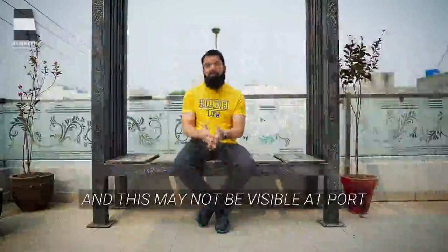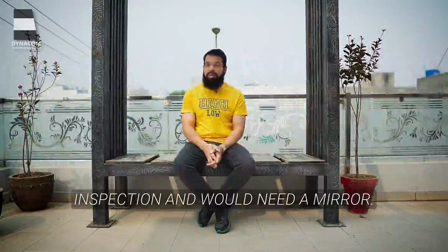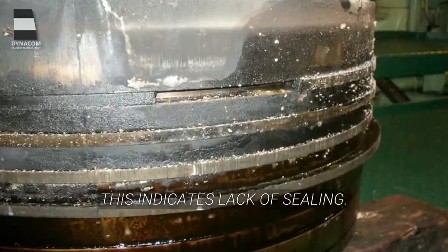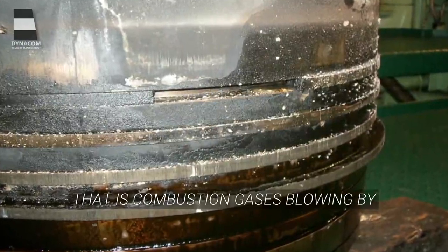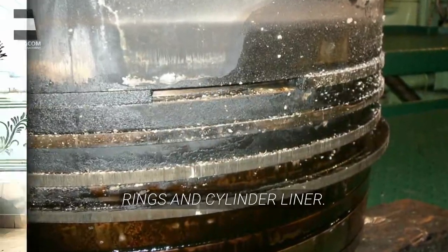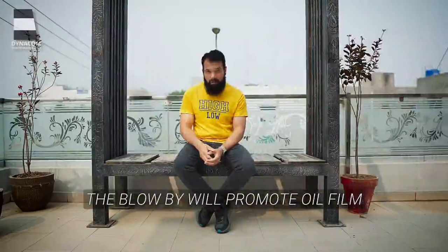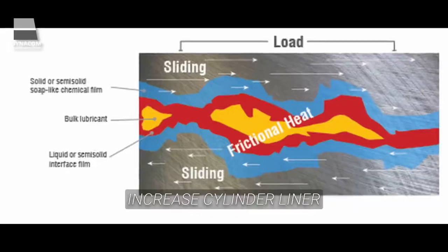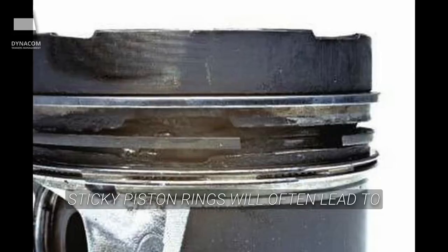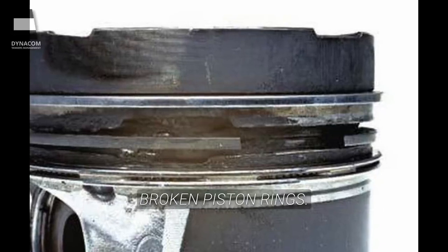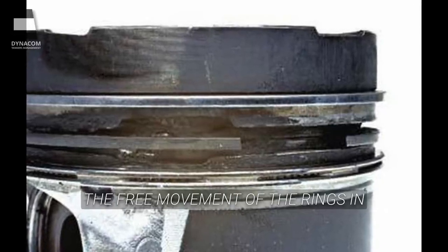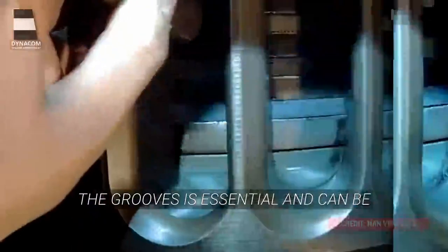And this may not be visible at port inspection and would need a mirror. This indicates lack of sealing, that is, combustion gas is blowing by between the piston rings and cylinder liner. The blow-by will promote oil film breakdown, which in turn will increase cylinder liner wear. Sticky piston rings will often lead to broken piston rings. The free movement of the rings in the grooves is essential and can be checked either by pressing them with a wooden stick through the scavenge ports, or by turning the engine alternately ahead and astern to check